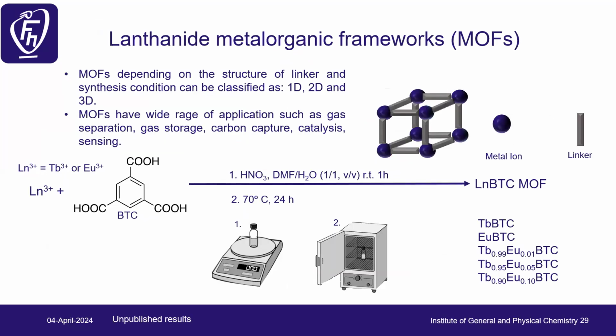And last, I will talk about lanthanide metal-organic frameworks or MOFs. These are polymeric coordination structures, which can be 1D, 2D, or 3D, so they can have pores. They are used already in gas separation, gas storage, CO2 capture, NOx capture, but recently in sensing. So you can use them with lanthanides in optical sensing. So we synthesized with this BTC, terbium, europium, pure, and in ratios, here the theoretical ones are shown, by hydrothermal synthesis. So we used a vial with our linker dissolved and lanthanide, put it in the oven, and got it.